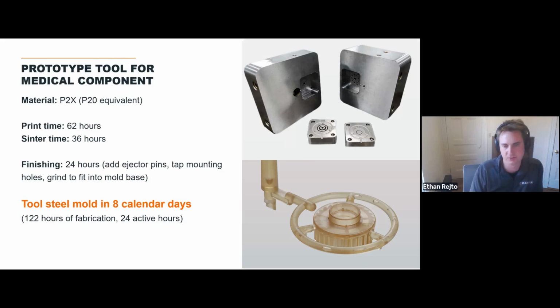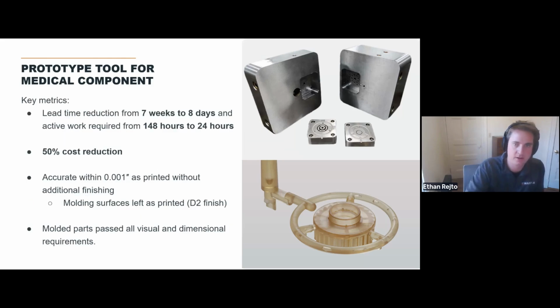So tool steel molds in just 8 calendar days here. That was a reduction from the estimated 7 weeks they would have had to go out of house here because of how much sinker EDM it would have required to build those thin ribs on this component. And the amount of active hours required went down from 148 hours down to 24. They also saw a 50% cost reduction.